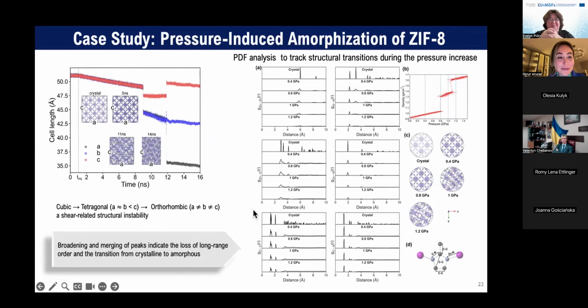What we observe here is that you can also see the changes in your structure. For example, initially you have the cubic structure, then you have a tetragonal change, and then you have the orthorhombic structure. After you have the structures, you can also perform pair distribution function analysis. Of course, if you have experimental XRD data, you can compute this and compare them. Here we want to analyze the broadening and merging of the peaks, and we try to observe the loss of the long-range order. We want to monitor the transition from the crystalline to the amorphous structure.